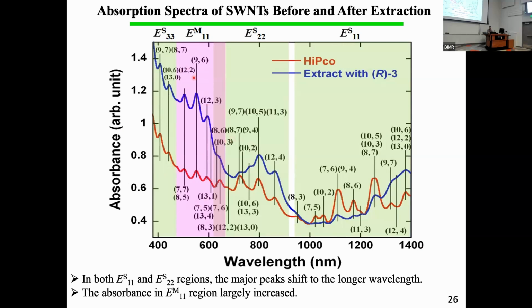So this is a metallic region, and you can see the large upward shift in the metallic region. Also in the semiconducting regions, we can clearly see the larger wavelength shift. Larger wavelength corresponds to the larger diameter. Anyway, basically, this nanocaliper prefers a larger diameter, but at the same time, it also prefers the metallic tube rather